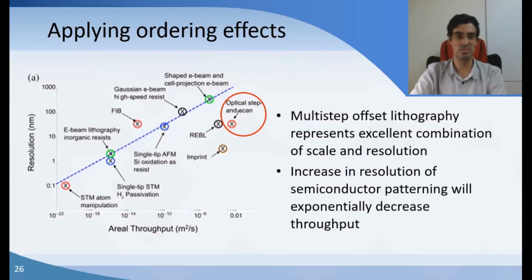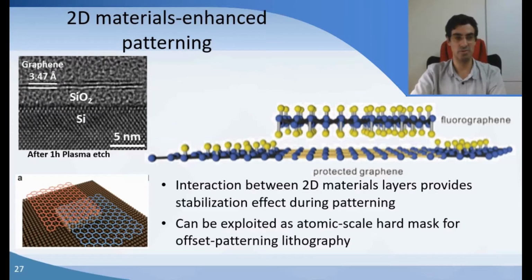The way that we're doing it is we're using fluorine as an adsorbent, and we're intrinsically having bilayer regions on the graphene. And so fluorine would interact with the exposed face, but the graphene that is underneath the bilayer would not experience fluorine interaction. This is important because it stabilizes the fluorographene on top. Basically, it keeps it from volatilizing, whereas regions that don't have another layer of graphene underneath are volatilized by a kind of zipping mechanism of the fluorine. Multiple fluorines get into a defect, and then they start breaking it from there.